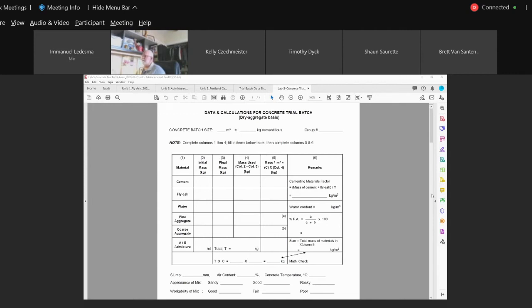Okay, so this is a form that we use if you're doing your calculations for a trial batch. In other words, you go to Carsey, you weigh out the aggregates, you weigh out the water, you measure out your air entraining agent, you weigh out your cement, you weigh out your fly ash, and you batch it. You've already got the masses for 1 cubic meter, okay? So here you can see the concrete batch size.